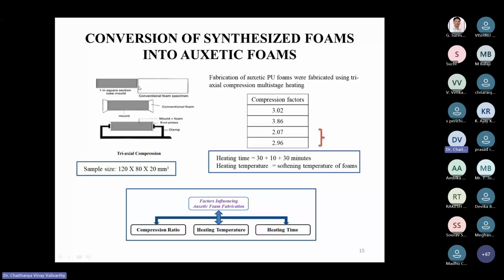The volume of the container should be less than the volume of the conventional foam, which we already prepared before. So we insert this conventional foam inside the container, and we close it with a lid. That means we are maintaining one compression factor. Compression factor is nothing but the volume of the foam divided by the volume of the container. There is no standardization of these foams, but we have used the trial and error method to conduct various compression factors. So we have achieved auxeticity with 2.07 and 2.96 compression factors.